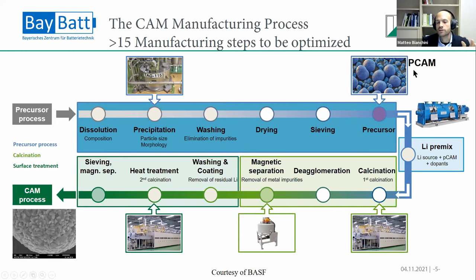And then we've made this precursor and we still have no lithium. So we need to add the lithium to make our cathode materials. And so you can do this in a sort of pre-mix step in a machine, which is called, for example, a rotary kiln. So you can add your lithium source and your dopants eventually and your PCAM. And you have a first heating step, and then you have a second heating step, the main calcination, which is done at a temperature, let's say between 700 and 800 or 900 degrees C in a roller hearth kiln, which is again like one of these very big machines that you see right at the bottom.